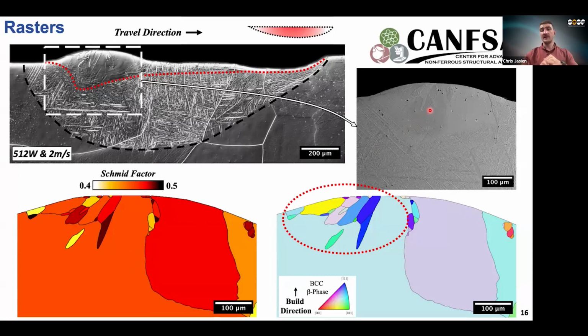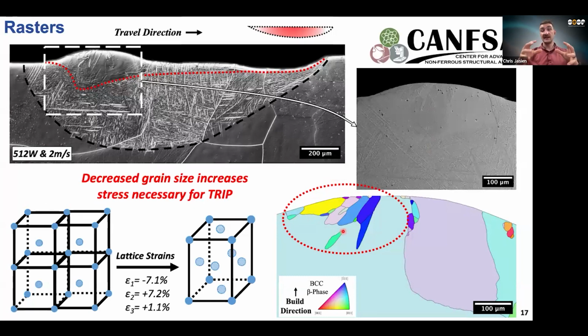But if you notice, there's one difference in this microstructure as compared to the ones that we have seen before, and that is a large amount of these smaller grains at the top of this melt pool. What that does is effectively decrease the size of these grains, where now you need an increased amount of stress or deformation to cause this transformation. Because to go from the BCC phase to this orthorhombic phase, your atomic structure needs to accommodate these strains in three principal directions. And if it's a smaller size, it needs increased amounts to accommodate this. So essentially, as you decrease your grain size, you increase the stress necessary to cause this transformation.